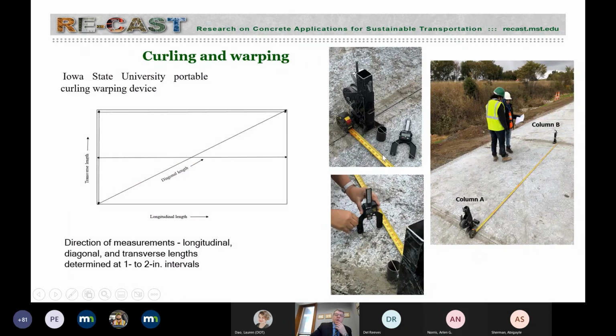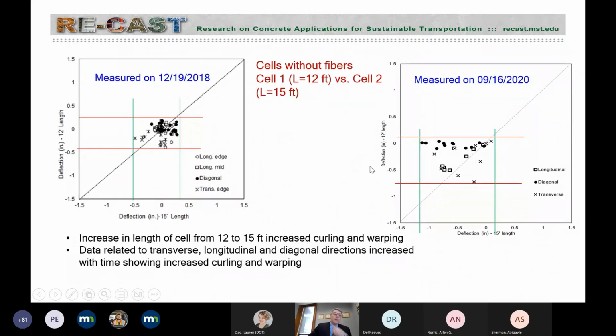We also looked at the curling and warping using a simple procedure that was developed and provided to us by Iowa State University CP Tech Center, Dr. Peter Taylor. So what we do is we measure the deflection between a certain point A and point B in a transverse direction, longitudinal and diagonal. And we look at that at 1 to 2 inch intervals. So between column A and column B, we look at the deflection that can be due to warping and curling.